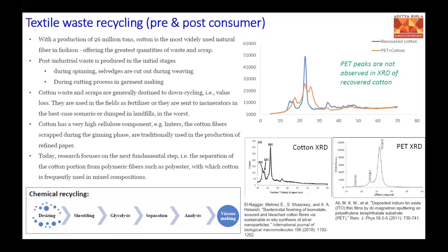So one way is going into chemical recycling, wherein we separate the polyester part from the cotton part, and whatever the purest form of cotton that we get, we use it in the process. So we are trying to do that. For chemicals, the route is recycling, then desizing, then shredding, and whatever shredded material we get, we do the chemical recycling or chemical separation of the petrochemical and the cotton. Glycolysis is one of the ways which is explored, wherein the polyester part dissolves and we can filter it and separate the cotton part. Then we do the analysis and use it for viscose making. So this is the typical process.